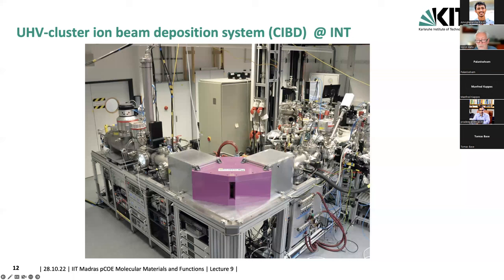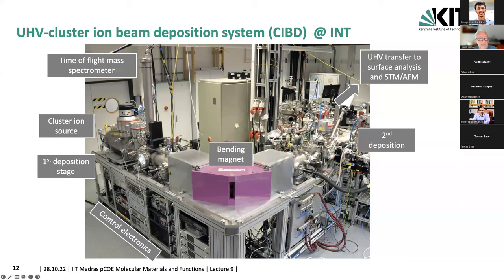When you look at the details, and whoever has visited Manfred's lab will recognize this, this is a cluster source, which is a copy, made with permission of the group in Freiburg. We copied it in our machine shop. This is a cluster ion source, which consists of a sputtering head. So we do sputtering inside this chamber, and we can control the gas pressure in here. We can control the distance of the sputtering head to the exit holes towards the high vacuum or ultra high vacuum. And you have a lot of pumps here to get the pressure from 10 to the minus 2, 10 to the minus 3 millibar here, to 10 to the minus 5, to 10 to the minus 8 and 9 as you go down the beamline.